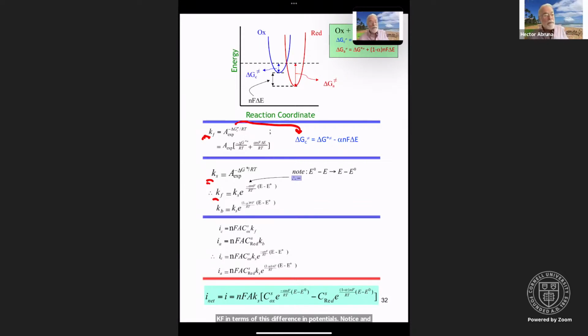Notice, and this is something that I remember when I was a graduate student, that going from E0 minus E to E minus E0, you put this little negative sign in there. And then for the reverse process, basically the counter to that, Kb equals Ks e to the 1 minus alpha nF over RT times E minus E0. So we can further develop this. So we now have an expression for the cathodic and the anodic current in terms of concentrations and rate constants. And so therefore, we can then again say the cathodic current is nFA, concentration of Ox, e to the minus alpha nF over RT, E minus E0. For the anodic one, nFA, Ks, etc.